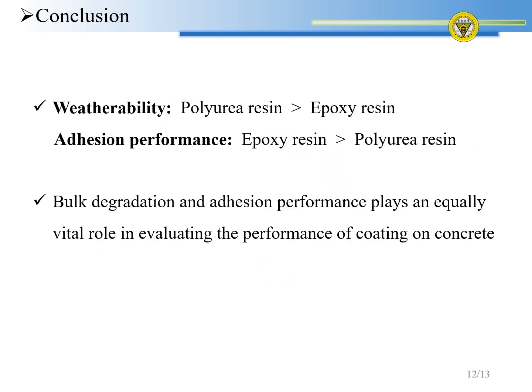Here are the conclusions. Through the surface and the internal structure characterization, we can obtain the weatherability. Polyurea is better than epoxy. But for adhesive strength and long-time resistance to chloride, epoxy resin is better. This reminds us, when evaluating coating under aging, bulk degradation and interface performance are both vital.